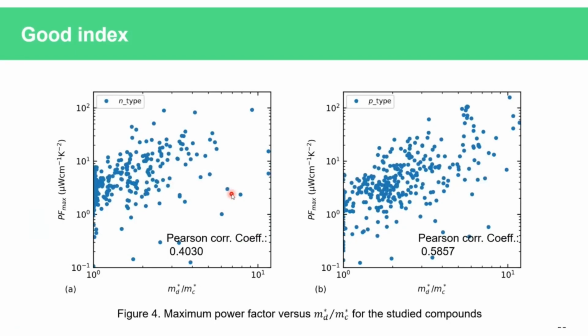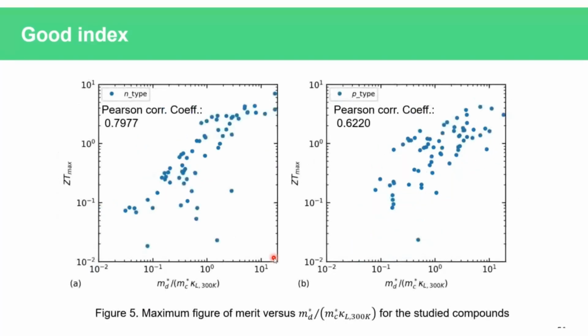Let's see the results. In these two pictures, I plot the maximum power factor against the ratio of MD divided by MC. The increasing trend is clear. I also calculated the Pearson correlation coefficient between these two variables: for N-type it is 0.4, for P-type it is 0.58. The Pearson correlation coefficient is not very high, but it still verifies there is a linear correlation between these two variables.